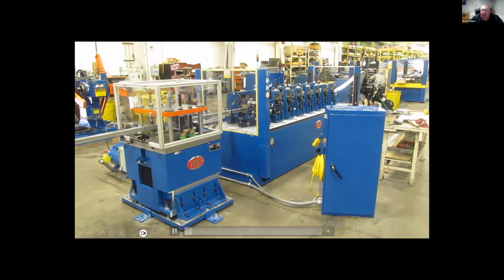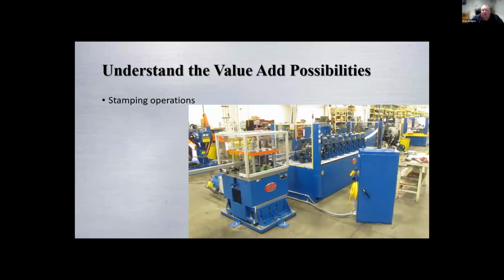This is a simple roll former. It's just a continuous coil. It's coming off the coil, running through the roll forming machine. It's coming through a straightening device, which this would be an Amco block. And then it comes through and it comes into the cutoff press. Once the desired length is hit, whether it be by a flag style like it was back in the 80s and the 90s, or today with controllers, we use encoders and electronic counting, and it knows when to cut the part. It cuts the part, the die moves forward during the cut, and then after the cut is complete, it goes back to home and it's ready.